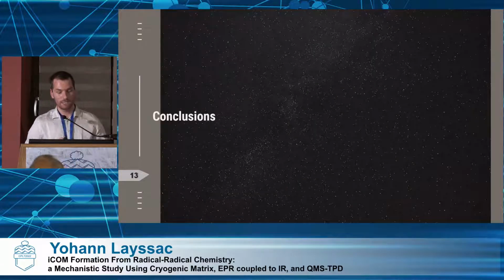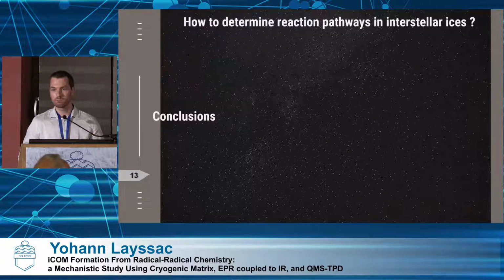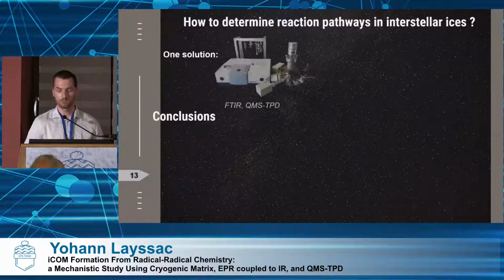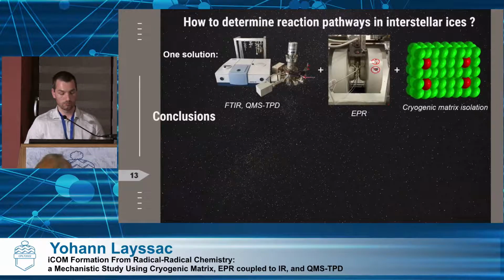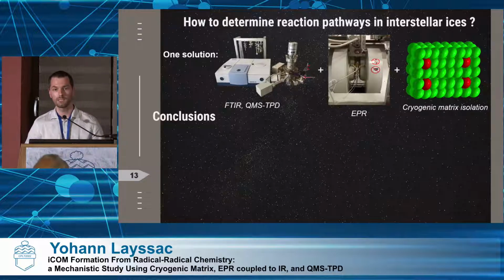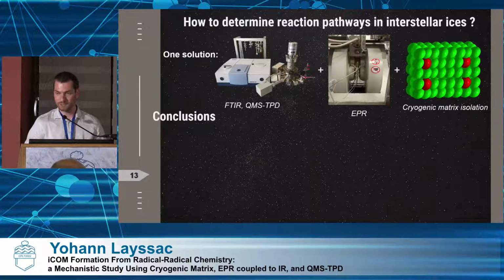As a concluding remark, to answer the main question, we propose a solution that is to combine some techniques. So the classical ones, FTIR and QMS-TPD, of course, but we propose to add EPR spectroscopy as an additional technique that is perfect to see the intermediary species. And of course, cryogenic matrix isolation that allows to control the reactivity step by step at low temperature, and to be able to speak about mechanisms more easily.